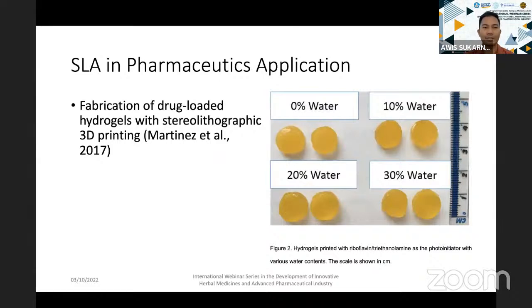Okay, so this one is actually a study done by other researchers, Martinez et al., 2017. In this study, they fabricated a drug-loaded hydrogel with stereolithographic 3D printing, or SLA. Basically they printed the hydrogel, where they incorporated riboflavin and triethanolamine as the photoinitiator. As you can see here, this one is without water, and then this one is 10, 20, and 30%. So basically the shape is almost the same.